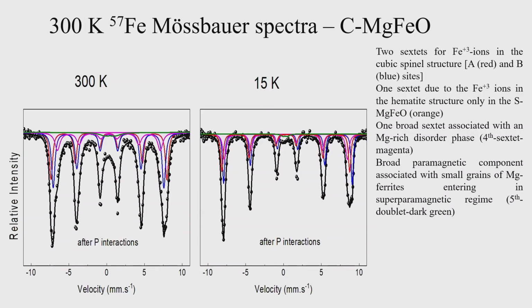for the ferrite, normal. You have the hematite, a little bit of hematite still, that X-ray could not find, I think, no? Let's see, I think that no, there is no hematite here, or basically no hematite here. No hematite. No orange here. Sorry, I put this one here, but it's not here. It's not in the spectrum. There is no hematite.